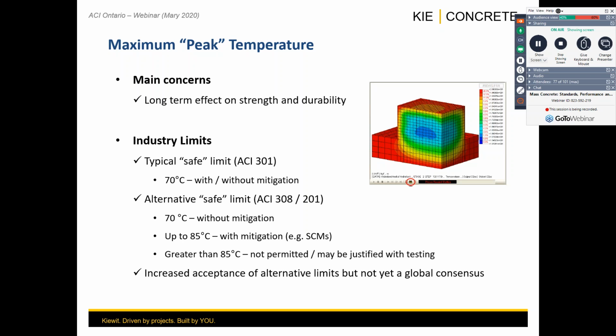However, as shown in the ACI documents of 308 and 201, and lots of research already completed to date, as you start providing mitigation into the chemistry, into the cementitious materials, bringing up all those SCMs into the mix, then the improvement into durability starts to occur, and then you can go up to 85 degrees Celsius. There's no recommendation provided right now by the industry or consensus to allow higher than 85 degrees Celsius, regardless of the mix that you have.